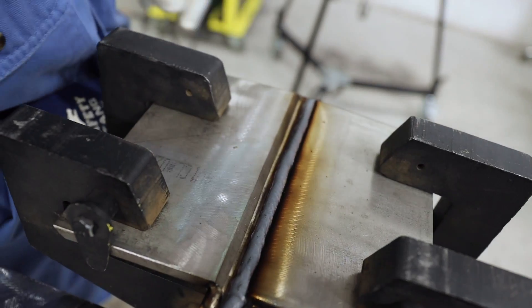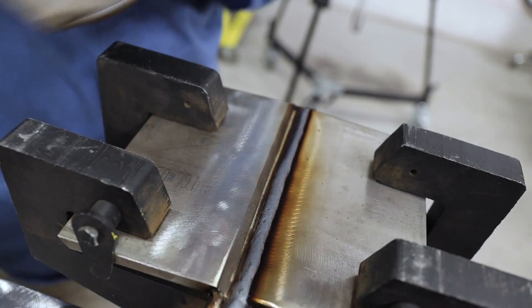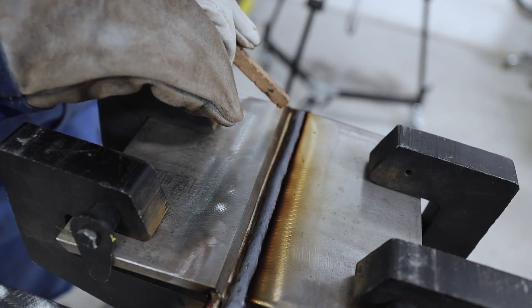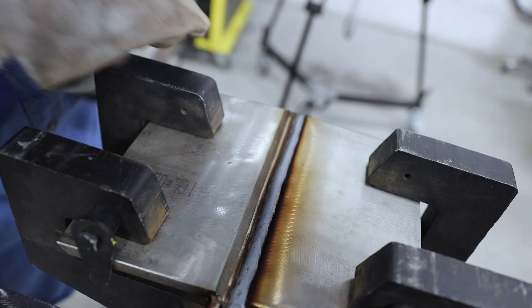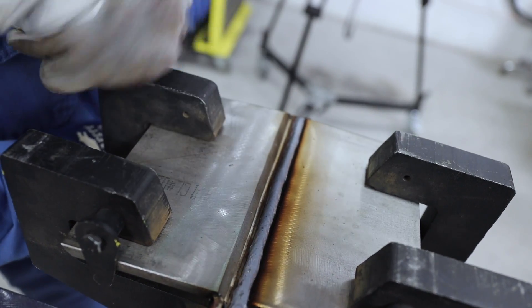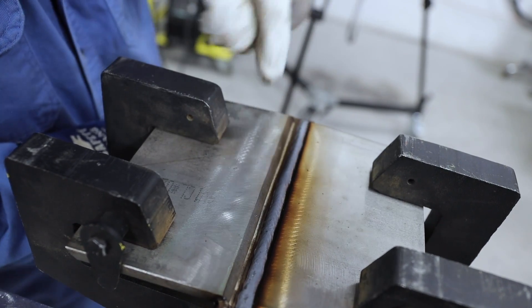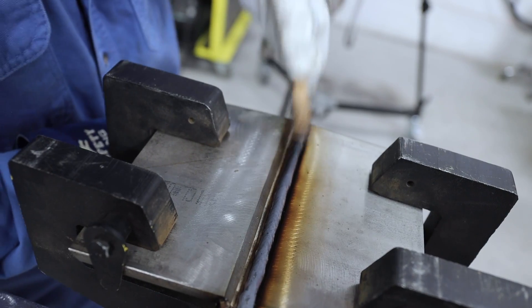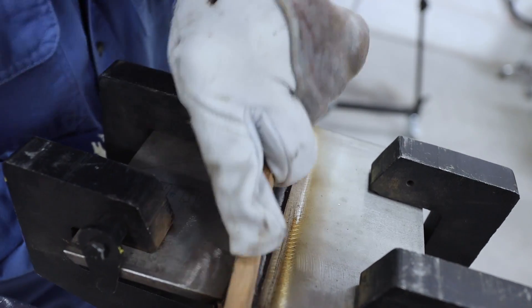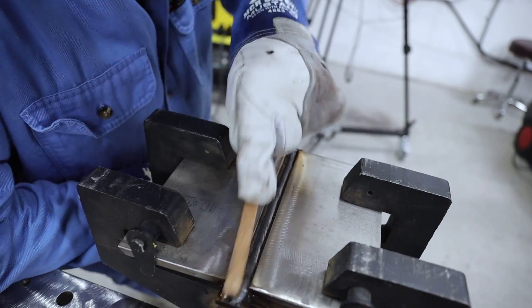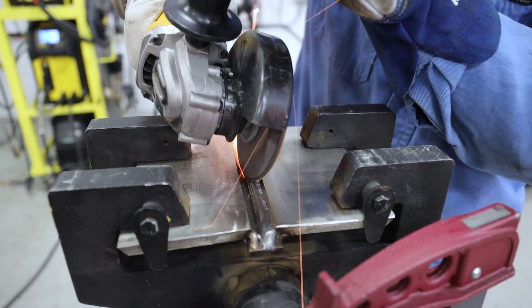Look at that. It's running. It sounds even better. I do a little technique. I just thought if I go from drag, if I get uncomfortable, I start going to a push. My wrist. That's it. So we don't have no BBs at all. That means we're running good. And look at our toes. Our toes are tying in good. There's no overlap. It's not finger nailing on the side. So it's burning in pretty good. See how it's getting hot? Getting hot. So walk away for five or 10 minutes, do something else. Right now I'm going to wire brush this. And I'm just going to hit that toe right here really quick. I'm going to hit all my toes just to increase my chance of passing. But I don't know if it's going to pass. I'm just going to kiss some sides. So we're ready to weld. But also I forgot we've got to give a little break.